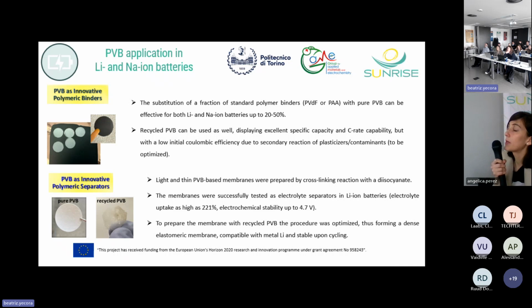And in the other application, as polymeric separators, first with virgin PVB, light and thin PVB-based membranes were prepared by cross-linking with isocyanates. And these membranes were tested as electrolyte separators in lithium-ion batteries with an electrolyte uptake as high as 221% and electrochemical stabilities up to 4.7 volts, which is high.